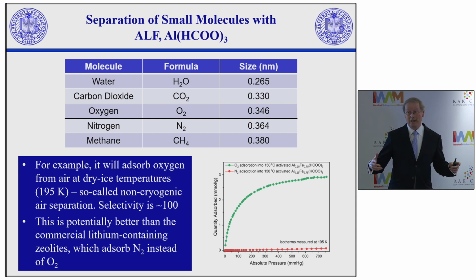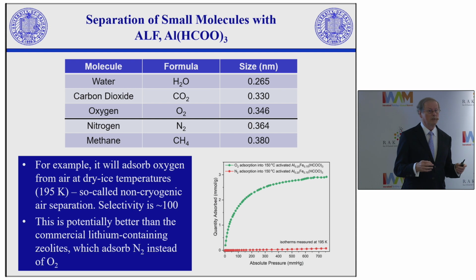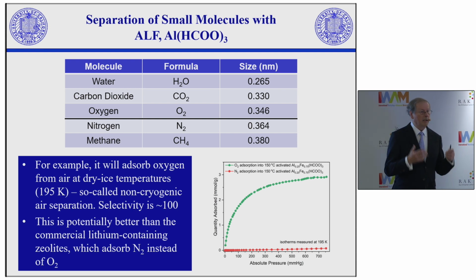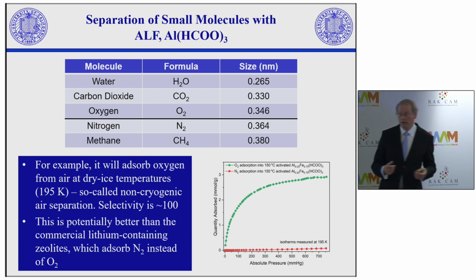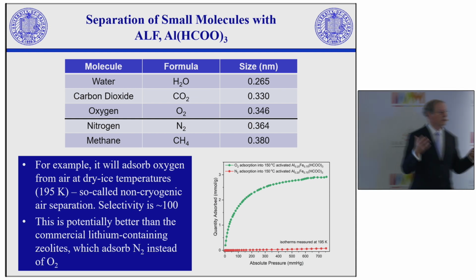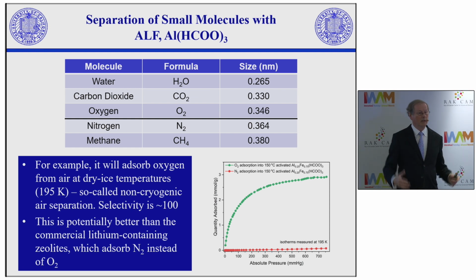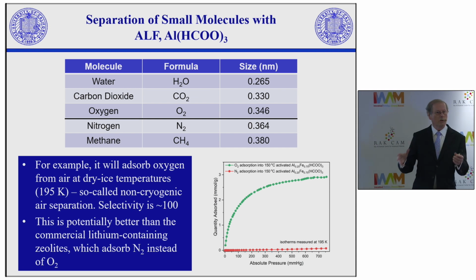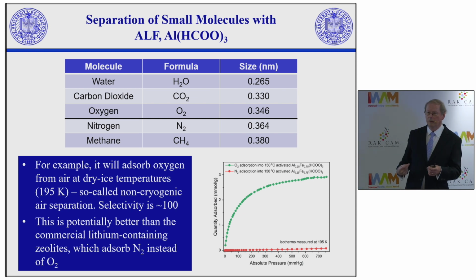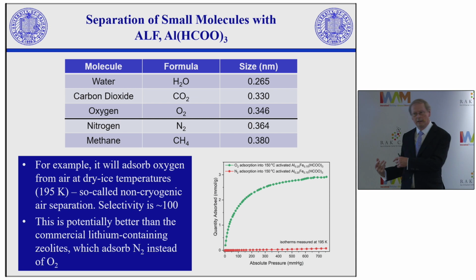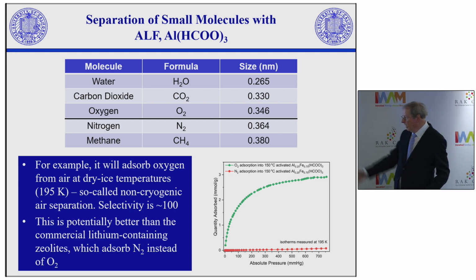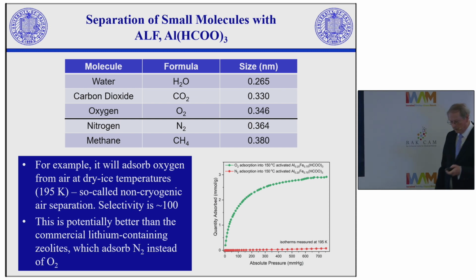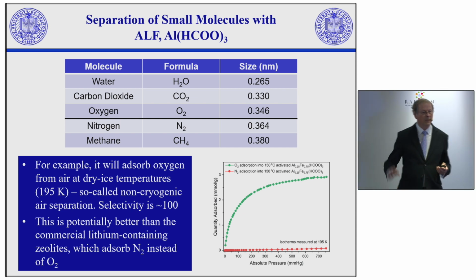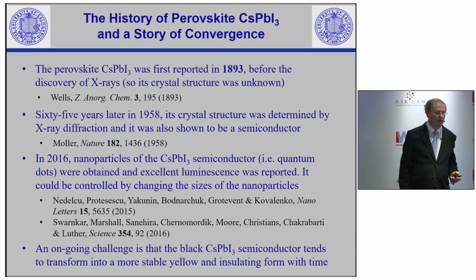And you know, during the pandemic, there's been a terrible shortage of medical oxygen because making medical oxygen is quite expensive. And there are different ways of doing it. You can do it cryogenically, which is expensive, but a large-scale commercial process. You can do it with zeolites, but the zeolites absorb the nitrogen. So if you want to separate oxygen and nitrogen, you'd rather take the oxygen out rather than try and take the 80% out. And so our material, with its affinity for absorbing oxygen, is an absolutely super system. And it will do other things we don't need to talk about today.